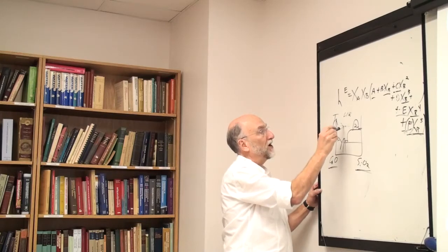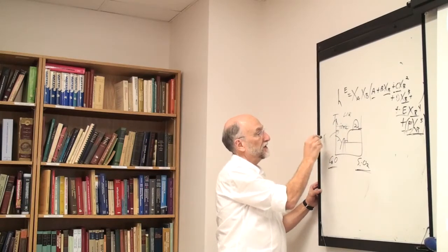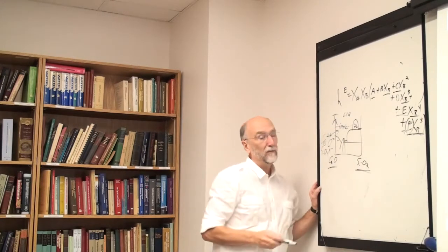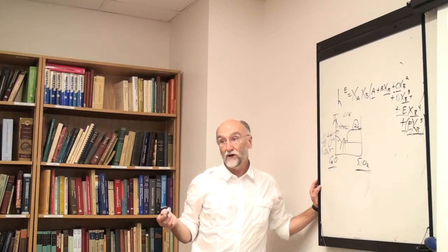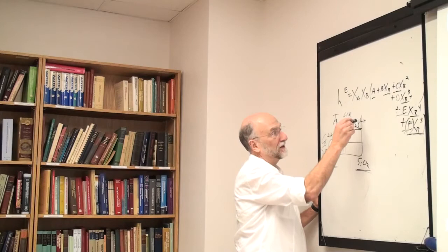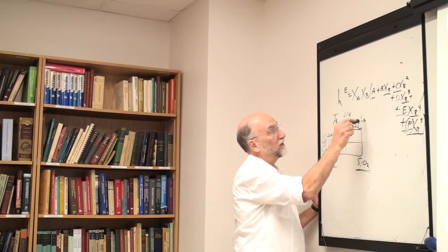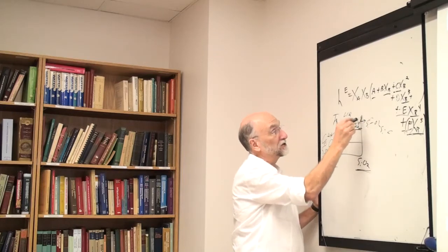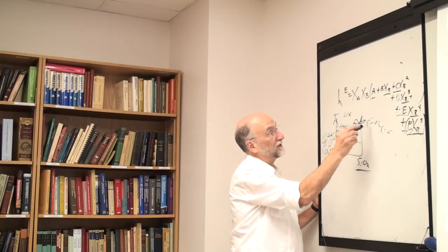Over here, you have kind of an ionic liquid consisting of calcium ions, oxygen ions, SiO4 ions, and it tends to be more or less well behaved in kind of a subregular solution, where 1 or 2 terms work. Over here you have a polymeric liquid with silicas all joined and broken bridges, a very complicated structure, which is a very different structure from here.